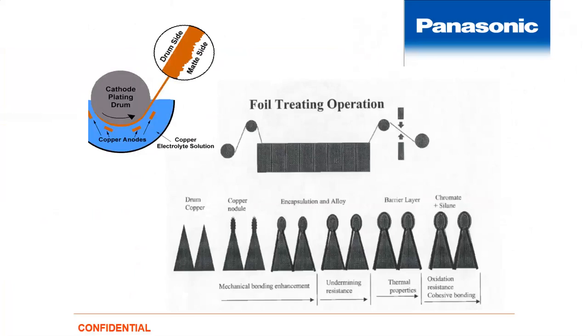Basically, the ED copper foil is electrically deposited onto a drum, and it gets plated. And as it gets plated on this drum, it gets pulled off and rolled up. You can see on the top part, the drum side is very smooth because that drum is a titanium drum, and it's in pristine condition, which produces a very, very smooth foil. A mirror image of the drum is on that smooth side, the shiny side, we call it the drum side. The opposite side, the matte side, where the chemicals are, is where the dendrite growth is. And you can see the topography on the matte side.